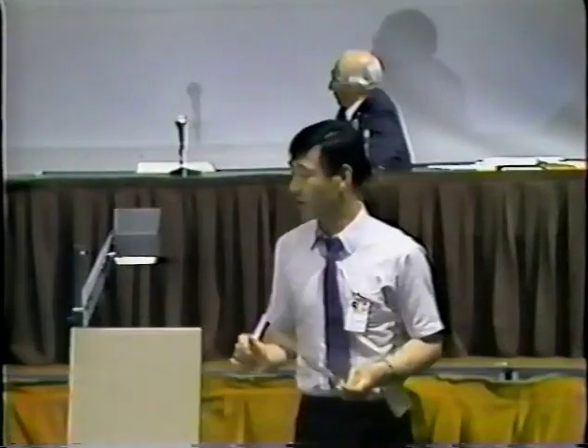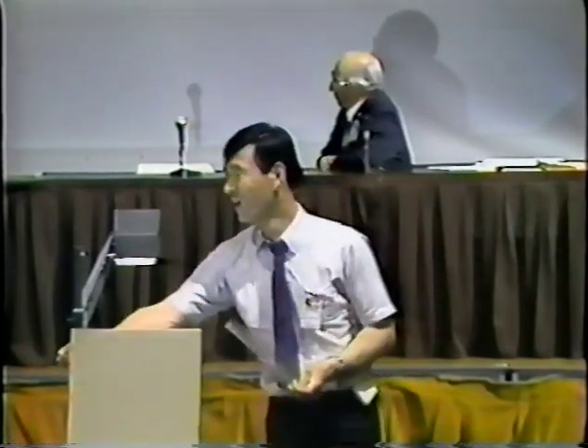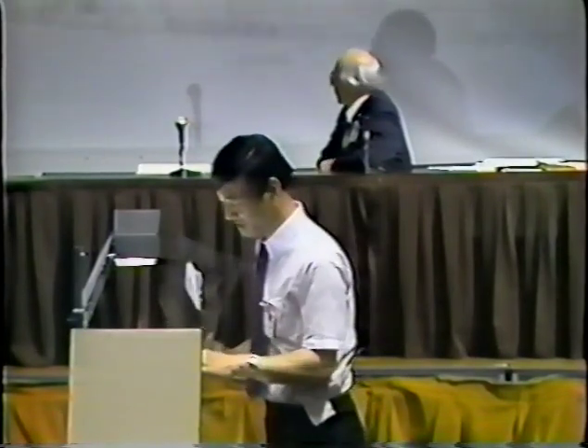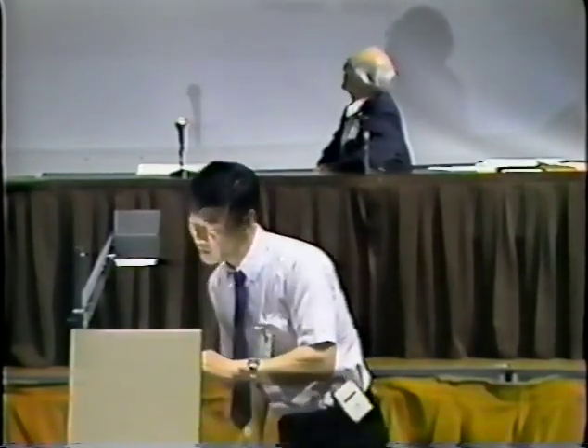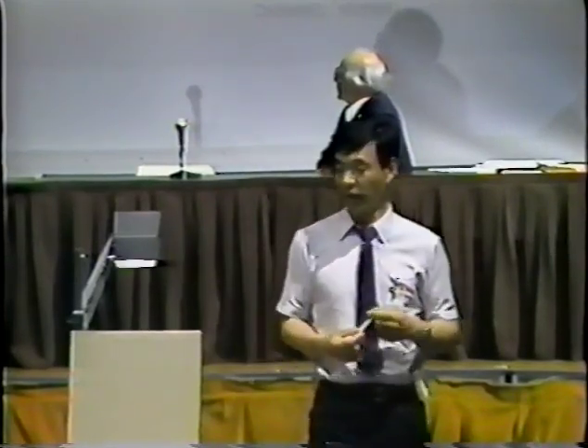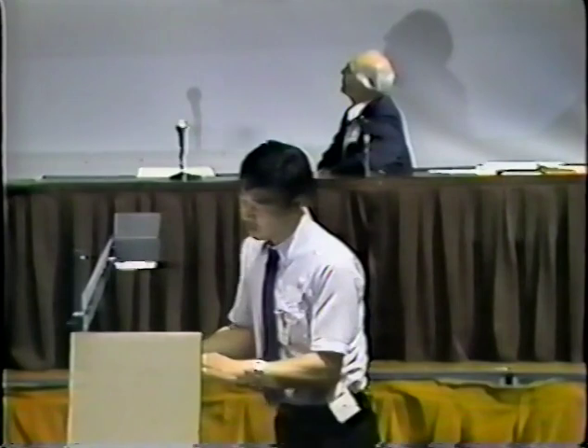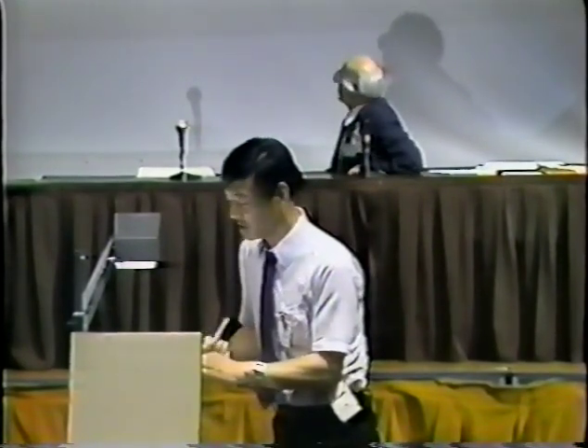So this is more of a warning for the measurement, especially for a physicist who doesn't know those things. I'm a nuclear physicist, and I was really surprised by this. And this is another type of electrolyte, the one Jones used. In this case, it's amazing that there's no sign of deuterium inside the palladium after 9 hours of electrolysis. Only hydrogen goes in, and even hydrogen seems to be diffusing very slowly in there. That's why you see this exponential type of shape with depth dependence.